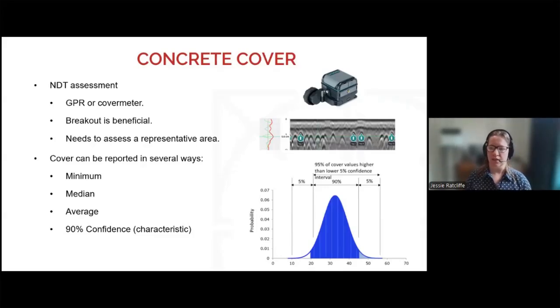The next piece of information we need is the concrete cover to the rebar. It's because the cover is the protective layer between the steel reinforcement and the chlorides or the carbonation or any other aggressive species that might be present. Once data is collected, we can assess the cover for the element or for the structure, and how we present this information varies based on the project.